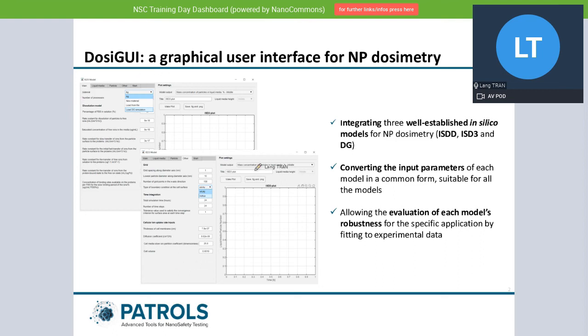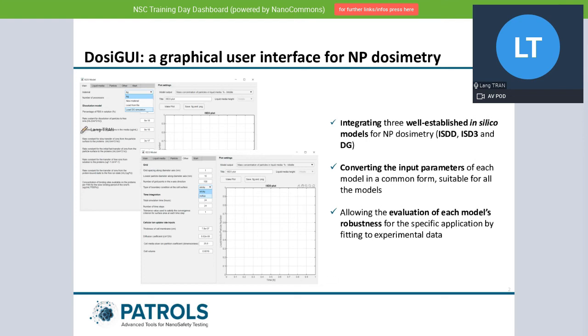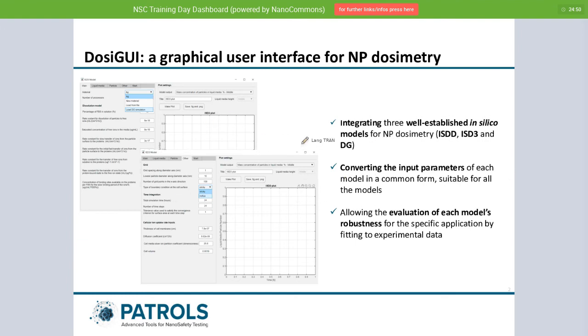There's nothing better than a graph. To the left, you can easily input all your parameters; to the right, you see a graph with time on the x-axis and concentration on the cells on the y-axis — you can see it building up over time. You can input different numbers representing the nature of the well, the nature of the liquid, the particle characteristics, and then it predicts the buildup of concentration on top of the cell over time. This simulates the amount in the liquid over the cell, and the particles that land first then sink to the cell, so you see that amount diminish in time.